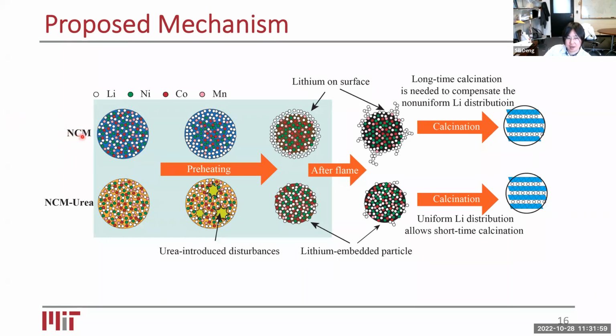For the NCM precursors, due to the intrinsic difference in diffusivity of the precursors, lithium tends to enrich at the surface, and after the salt gets decomposed, the resultant would also keep the same morphology. That's why we need a longer calcination time for lithium to diffuse back into the layer structure of this transition